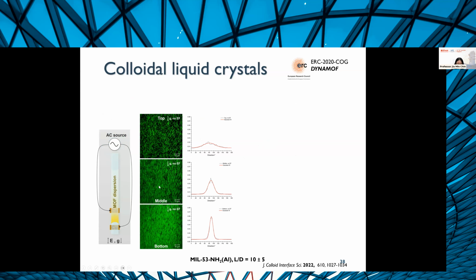dispersed them in a solvent and filled glass capillaries with our suspension. We had these glass capillaries sealed and vertically standing, so we allow the particles to slowly sediment from the top of the capillary all the way to the bottom. You get denser packing at the bottom, and you can observe what they look like over time. And we found that in our top layer, in the absence of an E field and just gravity, you see that you do have some kind of directional preference.